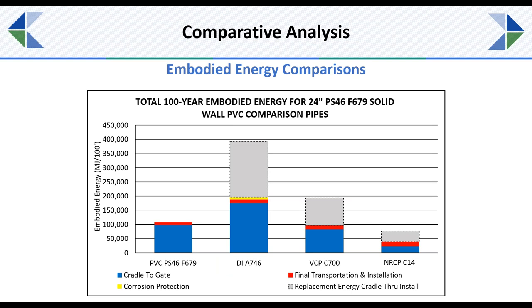And again, we ran the same analysis for the total embodied energy for a large diameter solid wall sanitary sewer pipes. Interestingly, here we see the vitrified clay and the NRCP or non-reinforced concrete pipe look like they have a slightly lower to a fair amount lower overall embodied energy. However, for the vitrified clay, you have to understand that their anticipated life cycle lifespan is not 100 years typically, mainly due to breakage and separation of the joints.